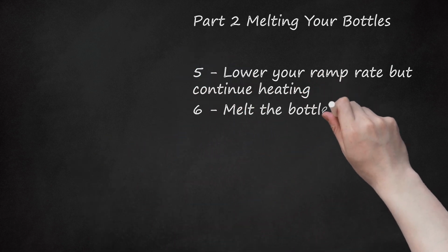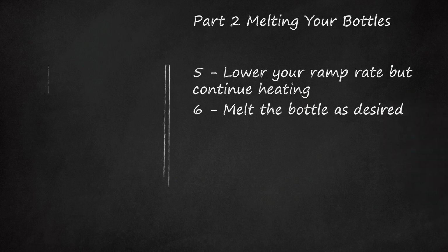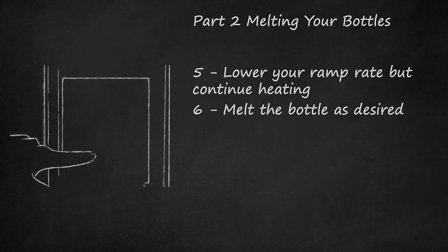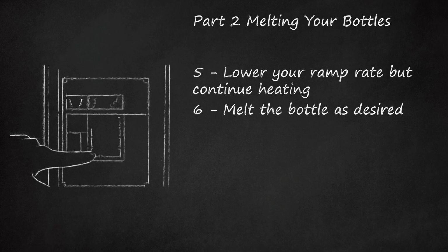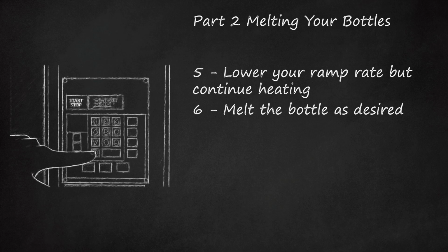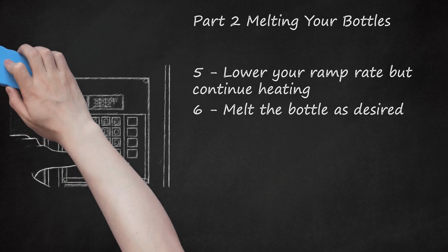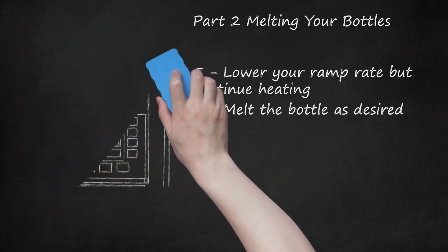6. Melt the bottle as desired. At this point in your firing profile, your kiln will be reaching temperatures that should be causing the bottle to slump in earnest. From 1300 degrees Fahrenheit, 704 degrees Celsius, you should ramp at 300 degrees Fahrenheit, 167 degrees Celsius per hour until you reach temperatures of about 1430 degrees Fahrenheit, 776 degrees Celsius. Once your kiln is at the peak temperature in your firing profile, you should allow for a hold time of about 10 minutes. Slight variations in hold time and temperature will influence how much your bottle melts.